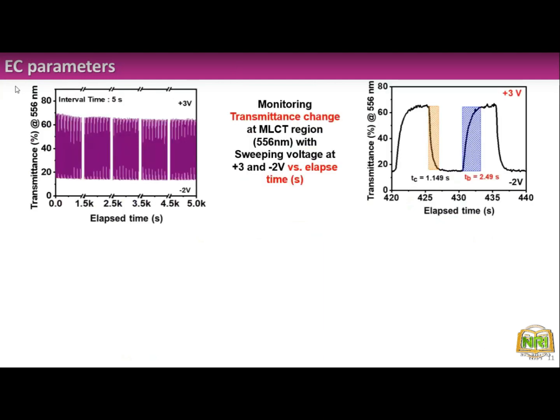So now let's come to the EC parameter study. It would be a little difficult to understand the graphs, so I'll explain here. From the UV visible spectra, at a particular wavelength, almost 556 nanometer, there is a huge change in the transmittance region. Now we considered that particular wavelength region, and what we did, we just applied a certain voltage on that particular region. So we fixed all the parameters in the instrument. I told you, when the transmittance is less, it becomes the color state. When the transmittance becomes high, it becomes discolored.